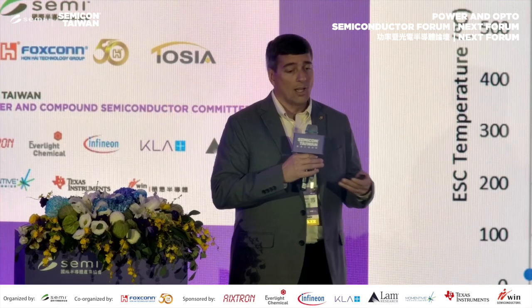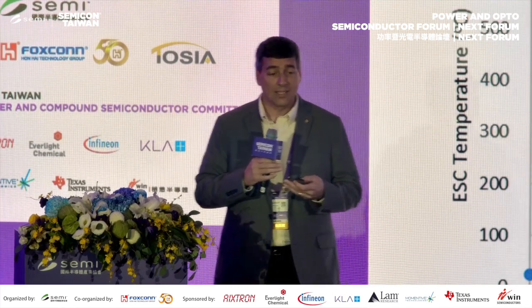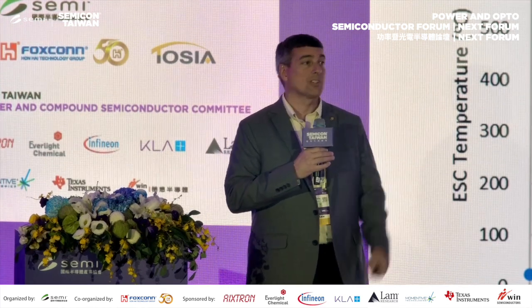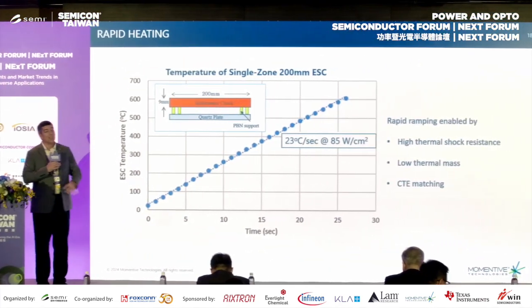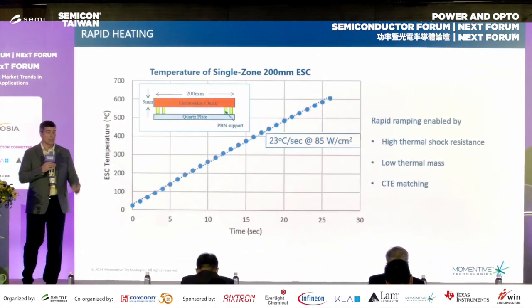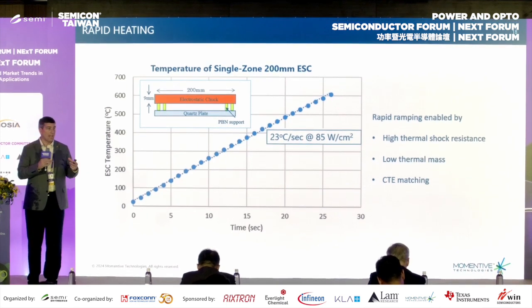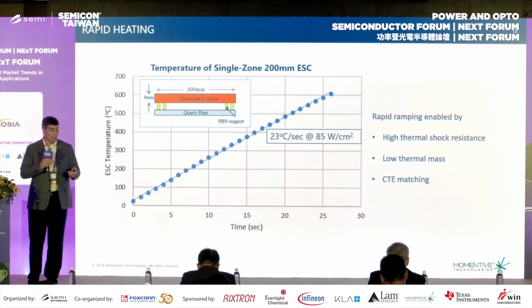What this gives us is all of the benefits of this nicely tailored unit. You'll see here, what this really allows us to do is very high thermal shock resistance and very low thermal mass, which means you can heat this very, very quickly. So this is a 200 millimeter single zone electrostatic chuck unit that we heated at 23 degrees per second, right, up to 600 degrees Celsius, multiple times. Don't do this with AlN, right? This just works extremely well because of the CTE match, the very high thermal conductivity of the assembly, and the material just fundamentally allows us to do this.